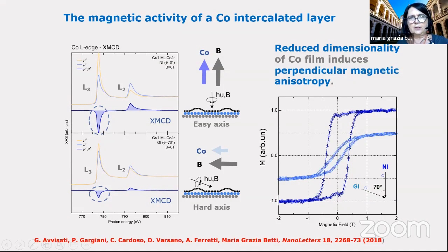Okay, first, let me show you the magnetic activity of the cobalt intercalated layer. You see on the left, there are the absorption spectra. This is the dichroism. The difference between the upper and the lower panel is the direction of the incoming photons. This is normal incidence, this is grazing incidence. So in this configuration, we will have the magnetic field in this direction, and so we have this dichroic signal. If we change, we have a dichroic signal with a lower intensity.